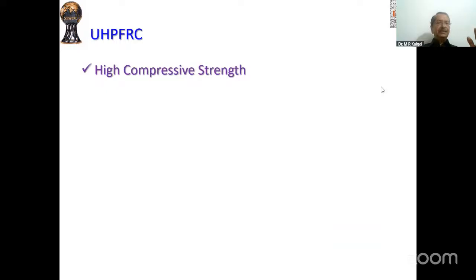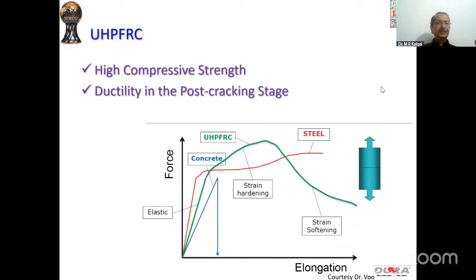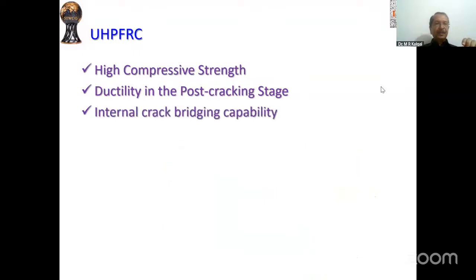So in essence, it has high compressive strength. It has ductility in the post-cracking stage. If you see the comparison, blue is for concrete, the red one is for steel, and you see fiber reinforced concrete, UHP FRC, is having much higher. It even shows some amount of strain hardening and very large area under the curve, which means the toughness is much higher here. It has an internal crack bridging capability.